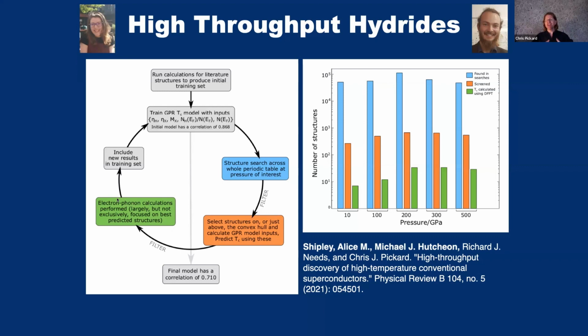And in doing this, we had a couple of constraints. We restrained ourselves to small unit cells, binary hydrides. So it's hydrogen plus one other element from across the periodic table with less than, say, 9 atoms in a unit cell, or maybe a bit more than that. Maybe we allowed a few more hydrogens, but of order 10 atoms in a unit cell. But we also made things easy for ourselves, because we insisted that all the structures were high symmetry. That's because the structures that have been found to be superconducting do tend to have high symmetry, and also they're much easier to calculate. So if we restrict ourselves to high symmetry, we have a chance of calculating large numbers of structures.